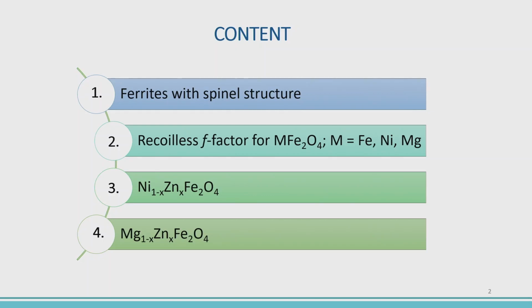Then the second part of my talk is related with a proposal given by us, in which we can easily, rapidly and directly determine the recoilless factor for samples which have two crystallographic sites. That is the case of the ferrites, which show iron in octahedral and tetrahedral sites. So this is our proposal of how we can calculate in an easy way the recoilless factor, and we apply this for 3 ternary ferrites of this composition.